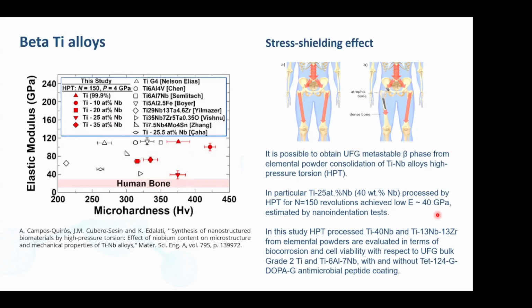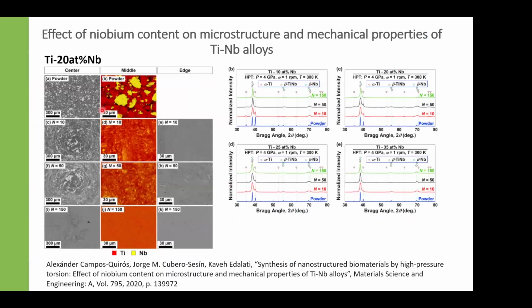And also, we have been doing a little bit of in vitro cellular testing, and that will be shown briefly too. So here on the left, you can see how the microstructure can evolve in terms of the powder or elemental distribution. These are SEM images from the center of the discs. These are EBSD composite maps from the middle of the disc, middle portion of the disc radius, and this is the edge. Again, SEM images from the edge. So this is the initial powder mixtures, and you can see here niobium in yellow and titanium in red. And when we do HPT 10, 50, 150 turns, we can clearly see the elemental mixing. It's very nicely done, even in the center and in the edge, of course.